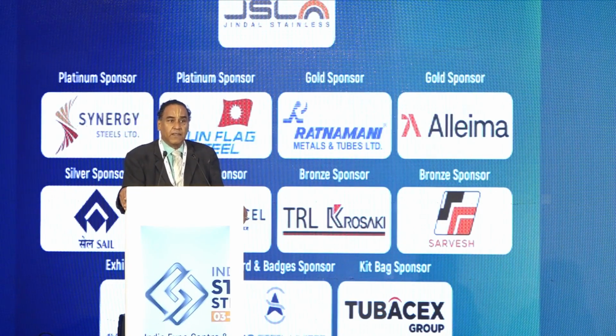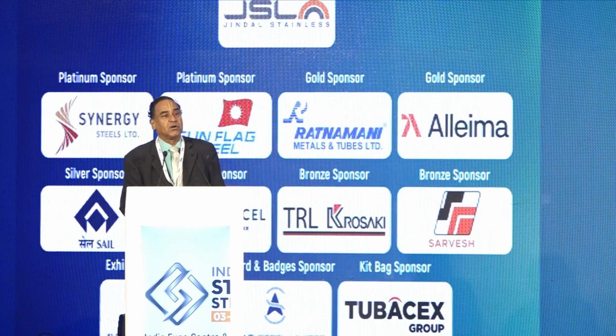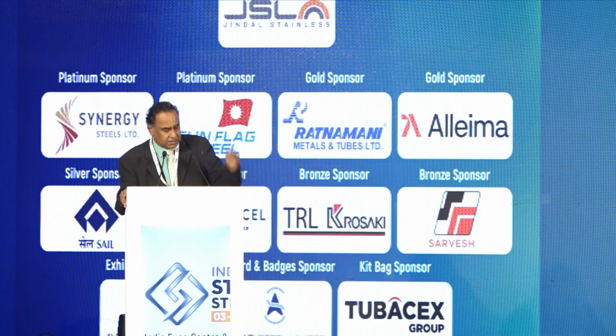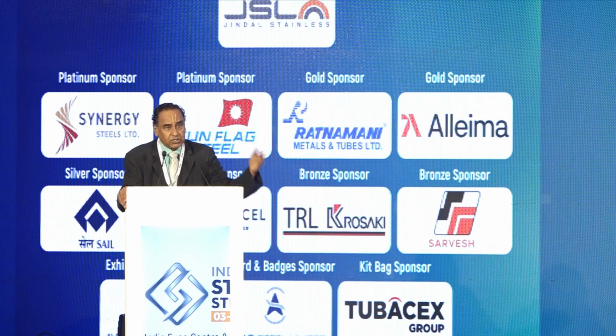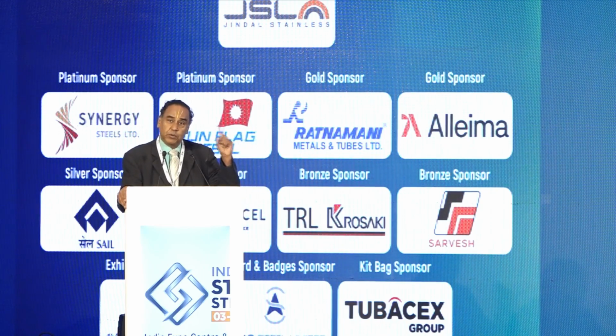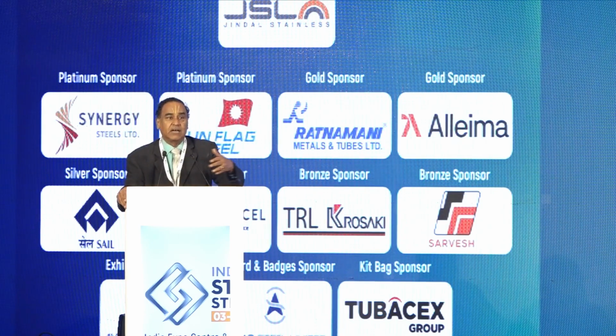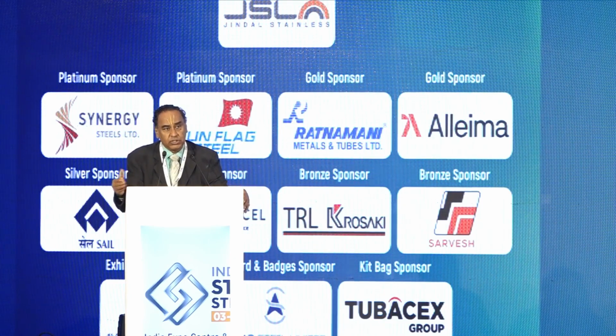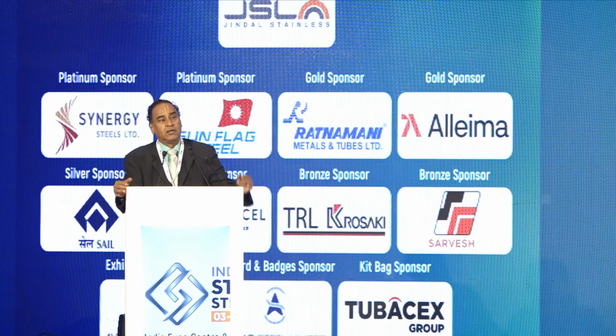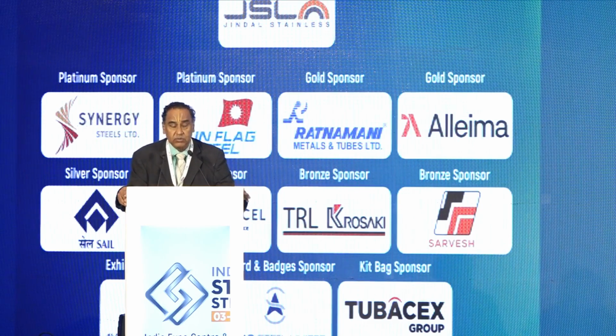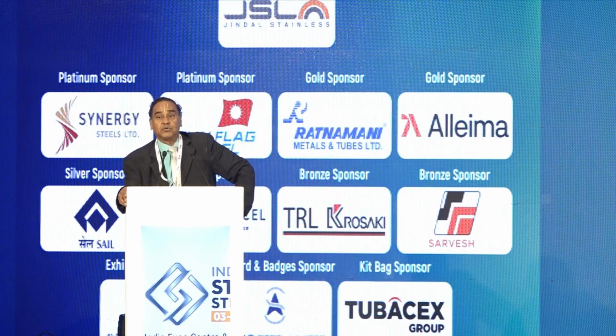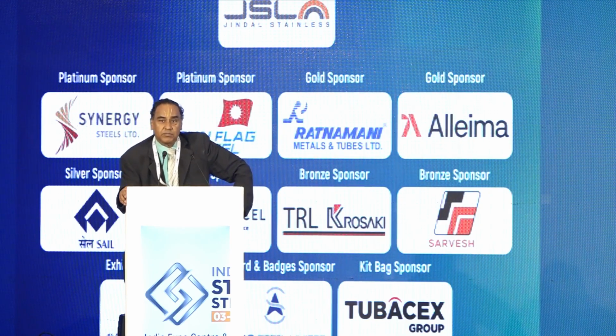But ferritic steels, even though they have very high chloride resistance, cannot be used in all conditions, because the fabricability and mechanical properties are suspect, especially as the temperature increases. It starts decreasing. Ferritic grades are pure chromium grades. When the carbon content is increased in those ferritic grades, they get very high strength. They can be used for high erosion resistance associated with chloride content also. Then they are called martensitic stainless steels. Martensitic stainless steels are cheap, but you still have difficulties with brittleness and hence fabricability in all the forms of our choice.